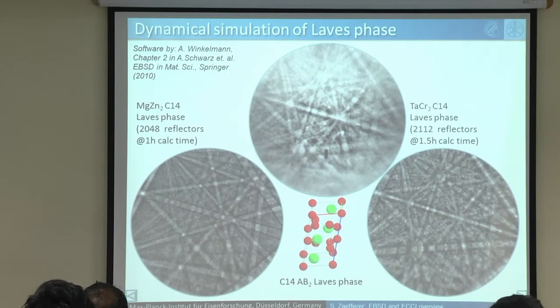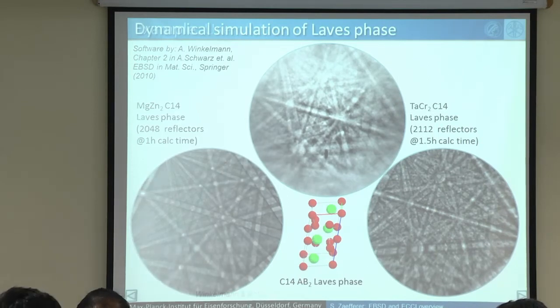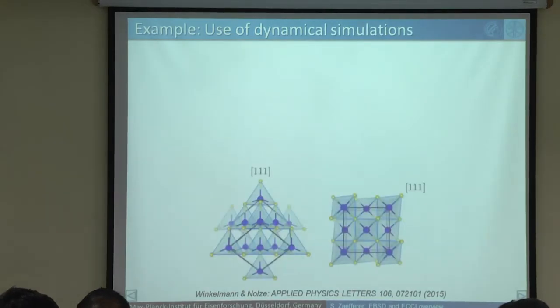That we can really do what you do nowadays in X-ray diffraction. You will be able to do on very small phases also with EBSD by just modifying the atomic lattice and seeing what is the outcome of the dynamic calculation. Of course, currently it's still slow. It needs 1.5 hours to calculate these patterns, but Aimo Winkelmann is speeding up that process. And Aimo Winkelmann and his good partner, Gert Nolze, presented a lot of beautiful applications of this new theory.